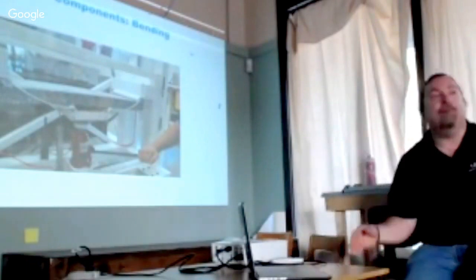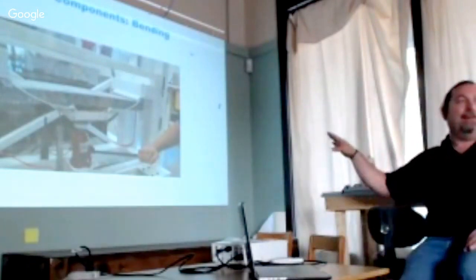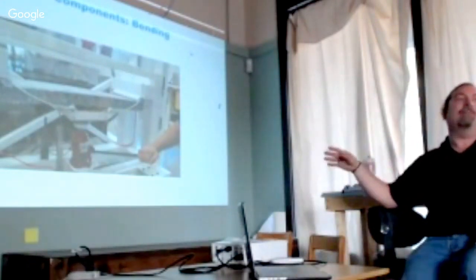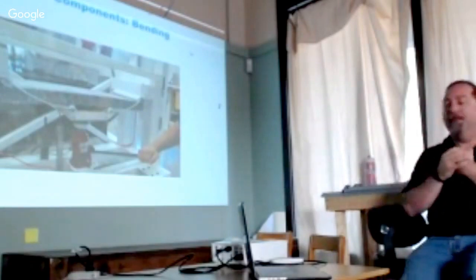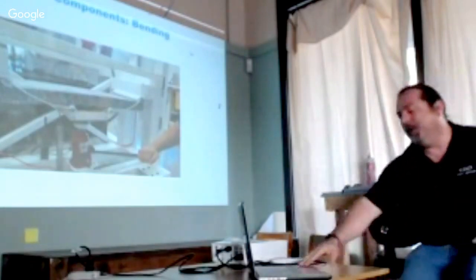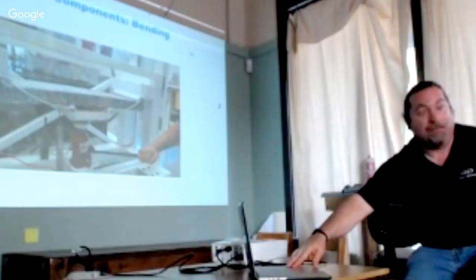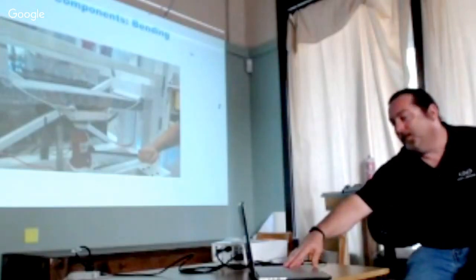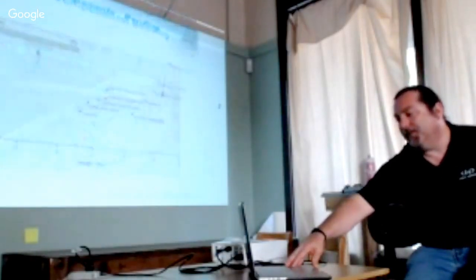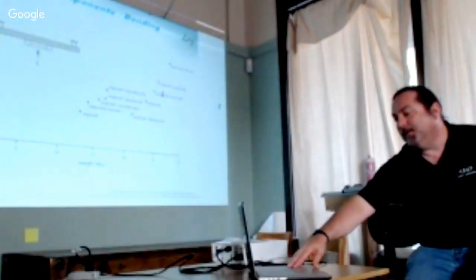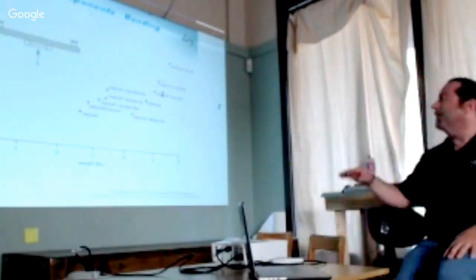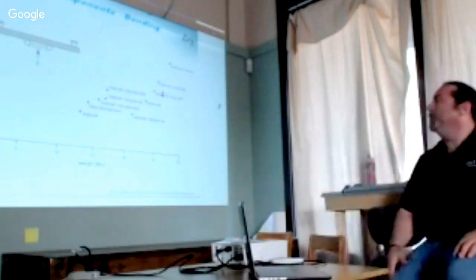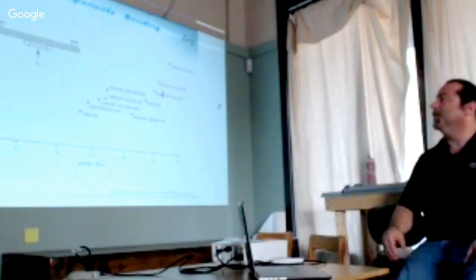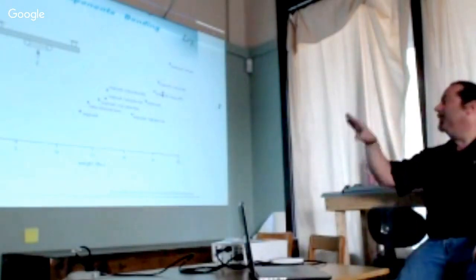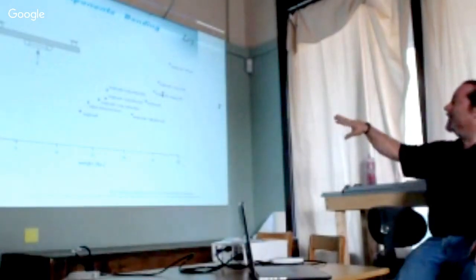If you compare it on a specific basis, like I showed the fatigue data, that's normalized for weight, and it compares fairly well to steel when you normalize it for mass. There we go. This is just one of the original plots we made of this data. It shows the stiffness as a function of weight, and then comparing the different box designs.